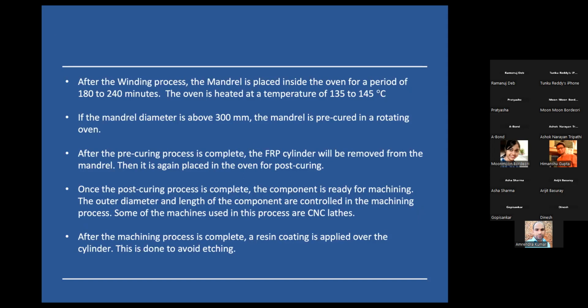Then it is again placed. Now, how it's removed, I just want to say, is through a mandrel extractor. Then it's placed in the oven for post-curing. Once the post-curing is complete, the component is ready for machining. The outer diameter, length, and components are controlled in the machining process. Some of these machines used are also CNC lathes. After the machining process is complete, a resin coating is applied over the cylinder. This is done to avoid etching and for a proper uniform finish.